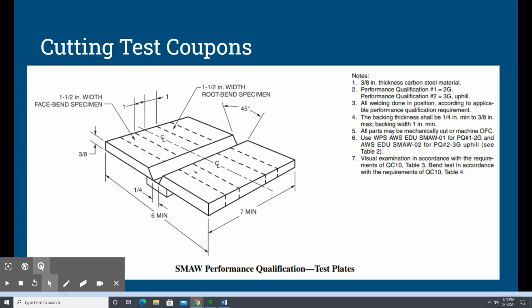Sometimes they already have a score in the gradebook and they bent them and they're just trying to pass the overall qualification for AWS. Well, then they might not want to waste the time cutting the coupons and getting everything prepped. So you can see how we cut them. The coupons are laid out from the center line. We go over an inch. Okay, we take a 1.5 inch coupon. We go the other direction, go an inch, and take a 1.5 inch coupon.